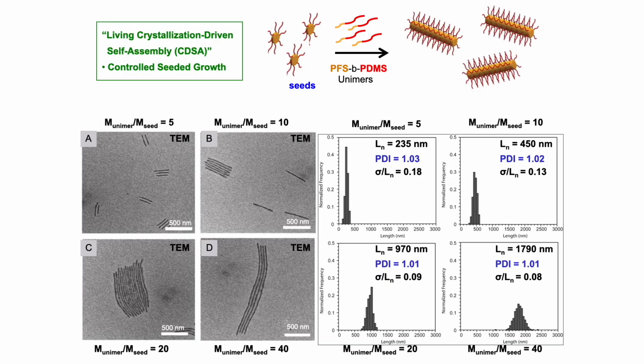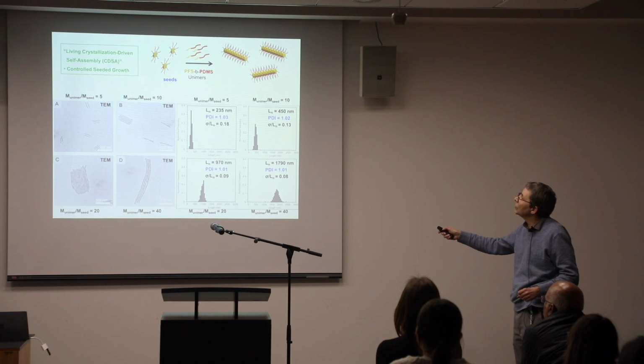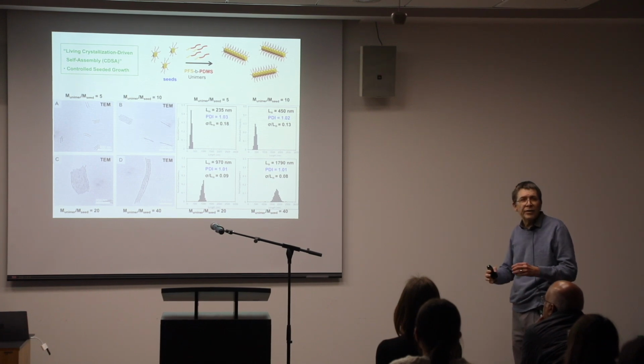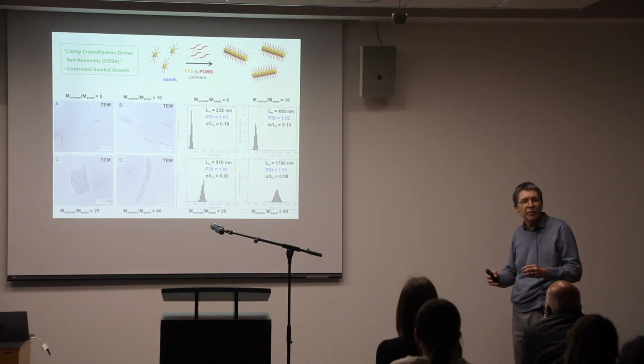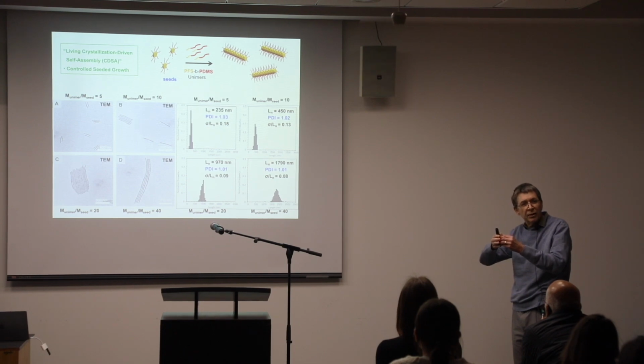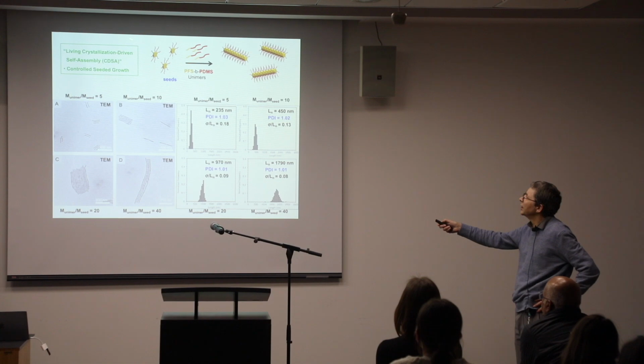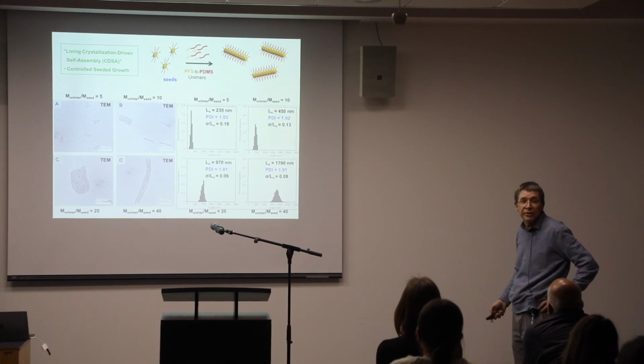The reason this works is these seeds are crystalline, and when you add the polymer, the PFS block which forms the core crystallizes off of the seed. You get a process called epitaxial growth, where you propagate the crystal from the seed and grow the fiber. So it's like growing a crystal - that's really what you're doing here.